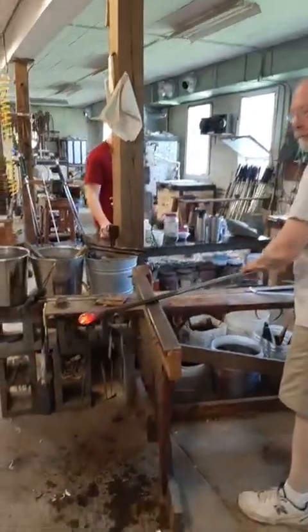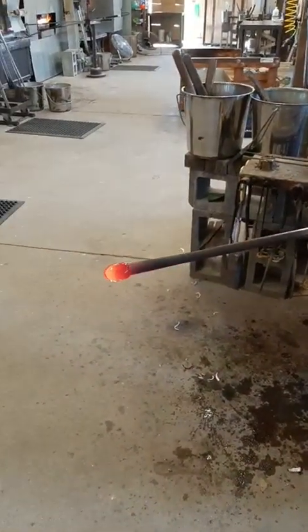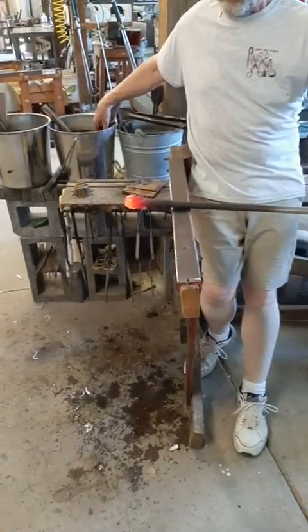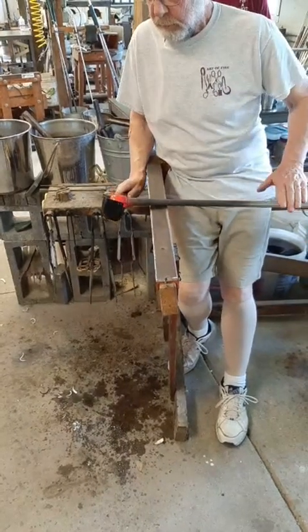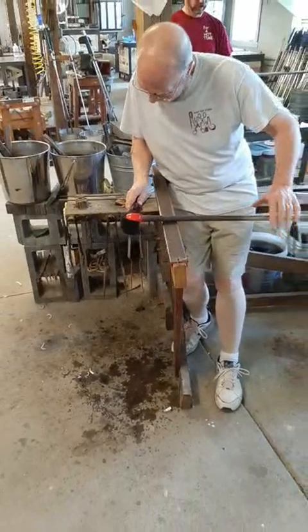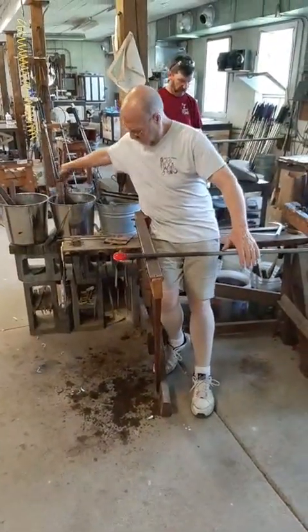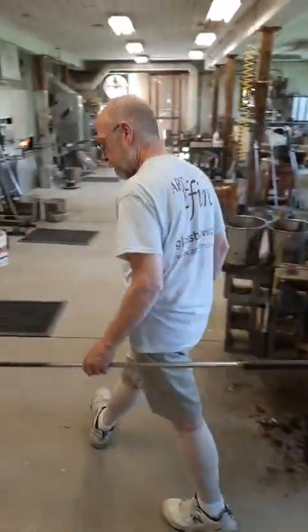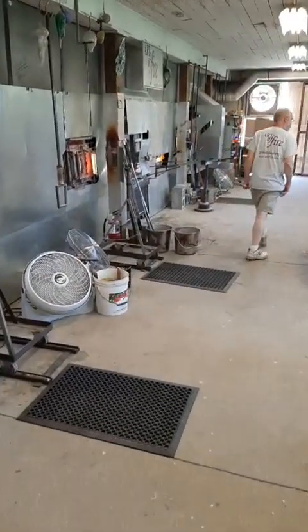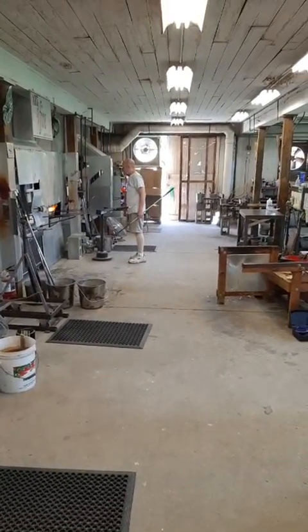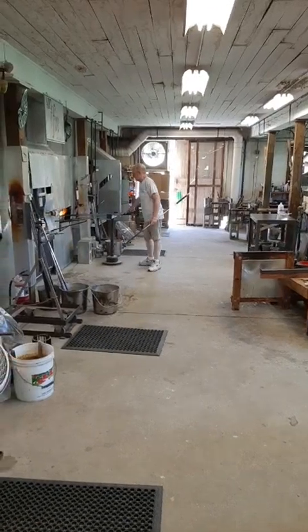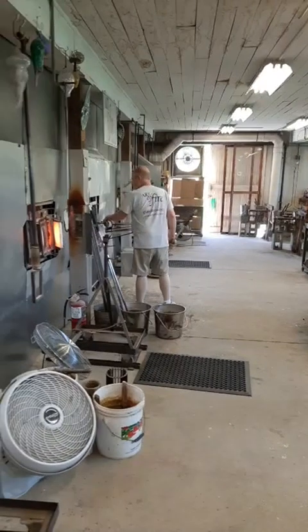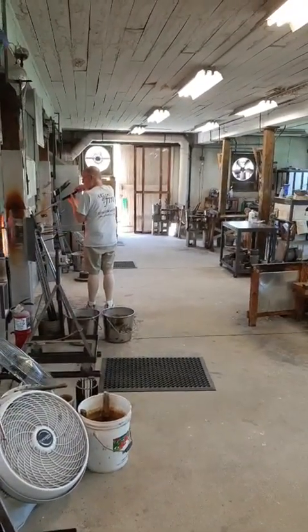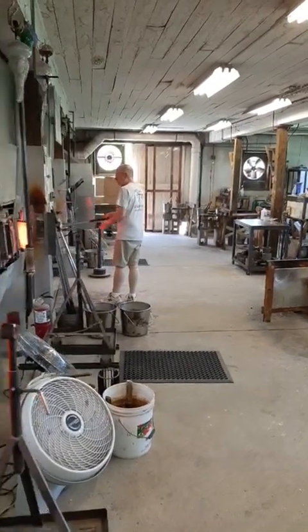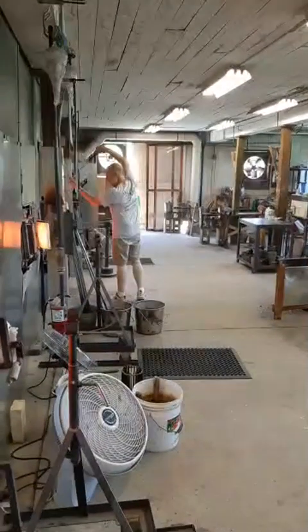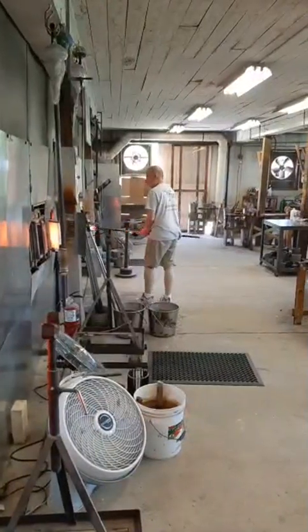Now, once again, he'll blow, trap the air in the iron, and we'll see that color core get larger. The air bubble is inflating inside the blue, and there we go. Bridget, not normally would we want the annealer to get that hot. But if we did choose to slump the glass, we could dedicate an annealer to doing that. But we've got a couple other options, especially with our electric annealers, that are probably better for that. The only time we get up over 1,000 degrees is when we've left the fuel and the air mixture too high and forgot about it. Normally we hold it right about 900 or 910. Foster's taking his second gather of glass. And this is the one that will go into the optic mold.